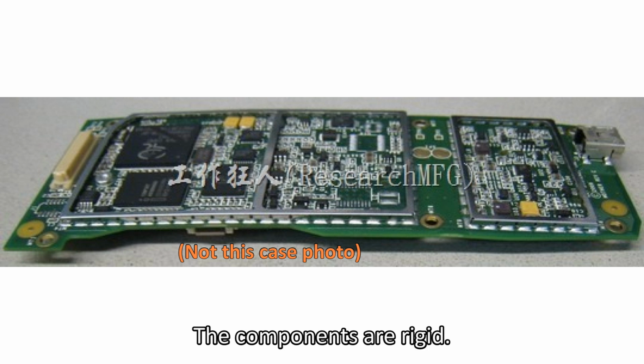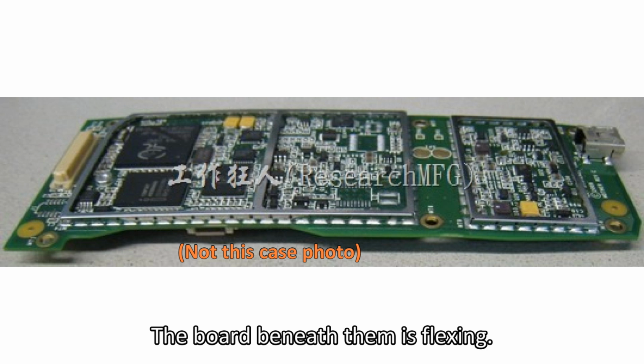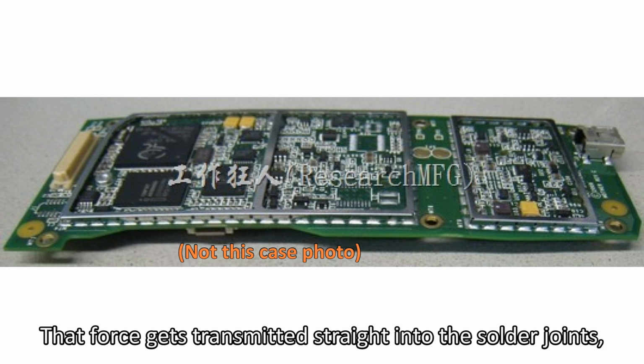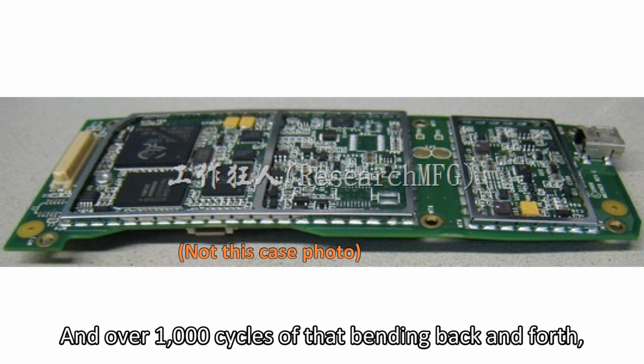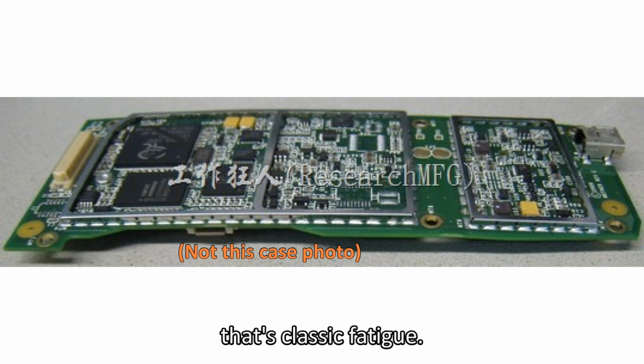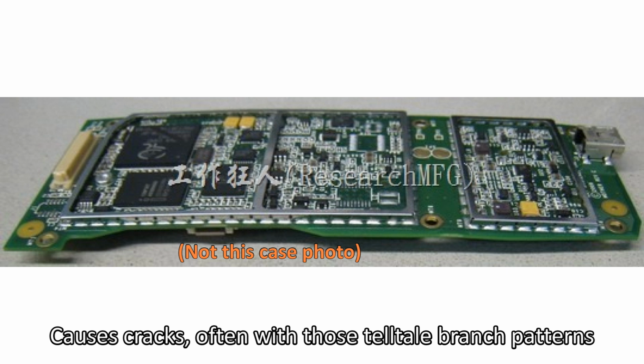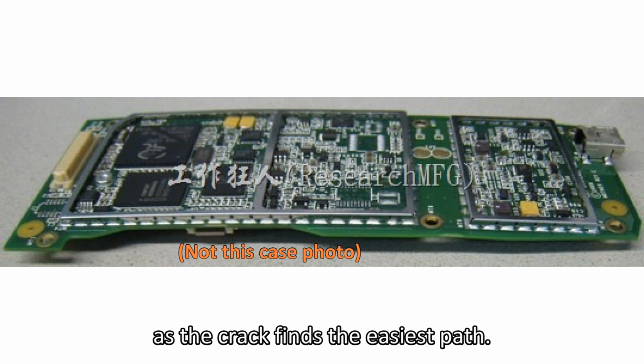Exactly. The components are rigid. The board beneath them is flexing. That force gets transmitted straight into the solder joints, holding them down. And over 1,000 cycles of that bending back and forth, that's classic fatigue. Causes cracks, often with those telltale branch patterns as the crack finds the easiest path.